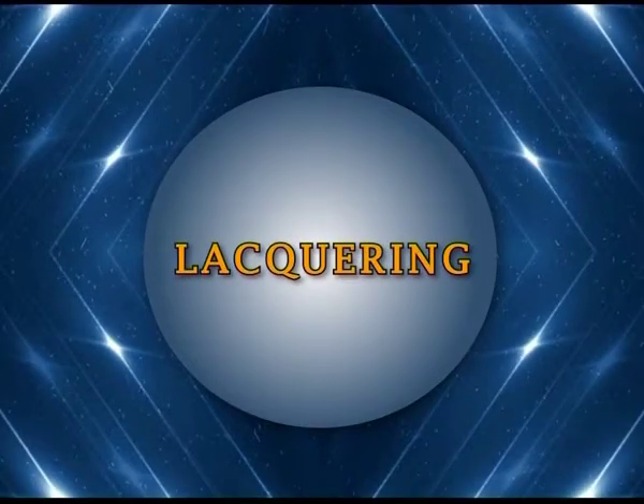Lacquering. It is difficult to coat steel plate uniformly with tin during the process of manufacture. Small microscopic spaces are always left uncoated, although the tin coating may appear perfect to the eye. Contents of the can may react with these exposed parts and cause discoloration of the product or corrosion of the tin plate. When corrosion is severe, the steel is attacked and black stains of iron sulfides are produced.